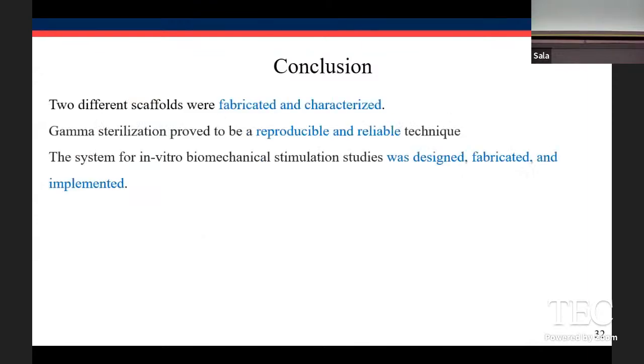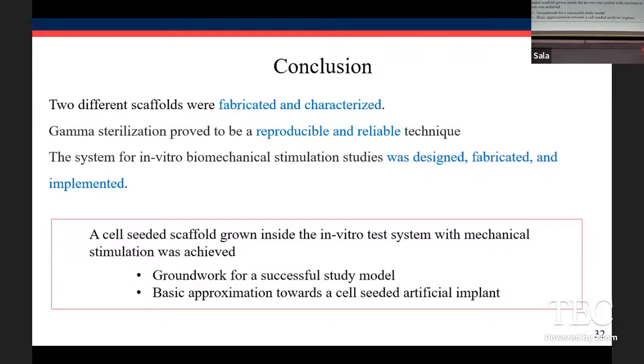And then as a conclusion, I would like to say that, in short, we achieved our specific objectives. We did the scaffold and we characterized them. We tested the sterilization procedure, and we also did the in vitro system. It was designed, fabricated, and implemented. And also wrapping this up with the things that I mentioned at the beginning, we sort of did the cell-seeded scaffold that I was mentioning, and these results can be used as groundwork for making a study model eventually, and also to continue towards achieving a proper cell-seeded artificial implant.